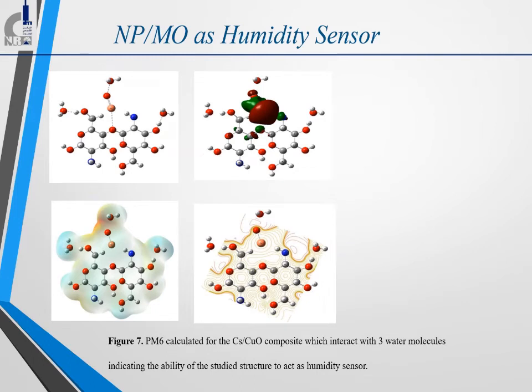Simply, the sensing idea is that when a sensor surface interacts with a detected material, the band gap changes and the electrical properties change as well to give an alarm. This interaction is simulated by weak interaction between the sensor surface and the detected material. So for applying chitosan copper oxide as a sensor, we considered a model of 3 water molecules interacting with the chitosan copper oxide surface, as shown.